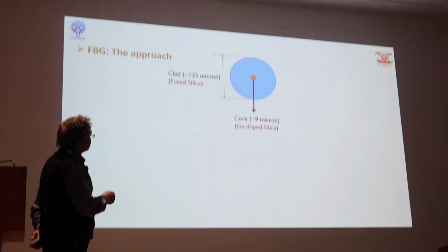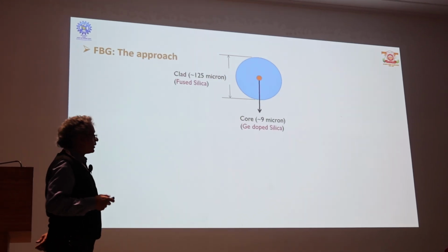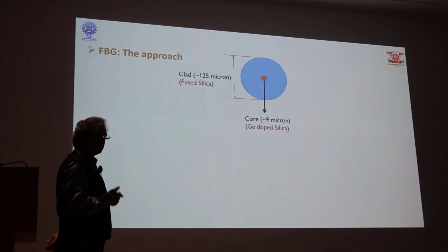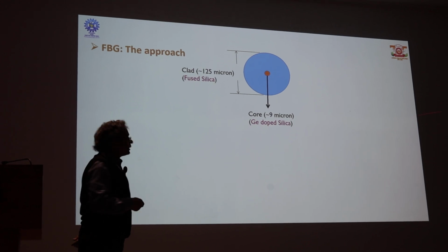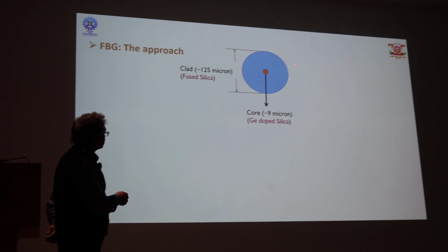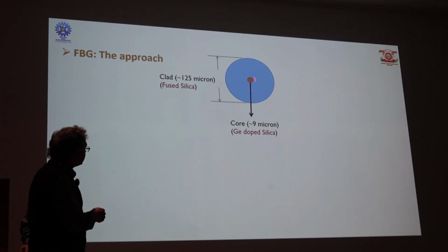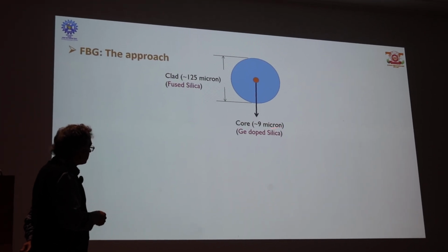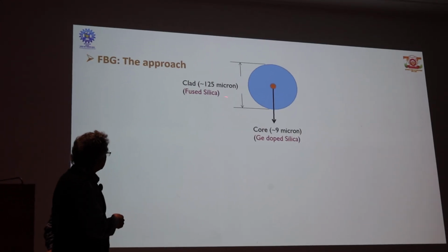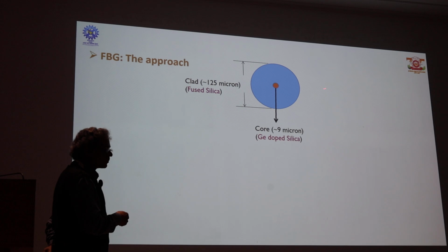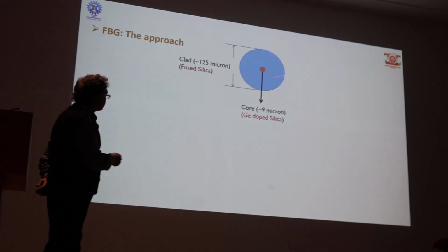If we consider the cross-section of an optical fiber, which everyone knows is the basic backbone of all of our communications, internet and data transmission. So what we have as a device is simply a silica glass fiber having a region centrally which is barely 9 micron in diameter, and the overall diameter of a glass optical fiber which carries almost all of this information is 125 micron.